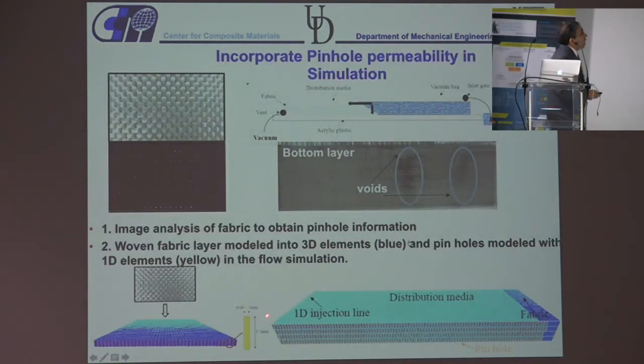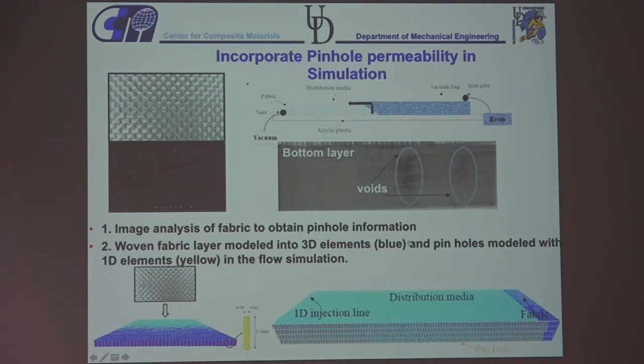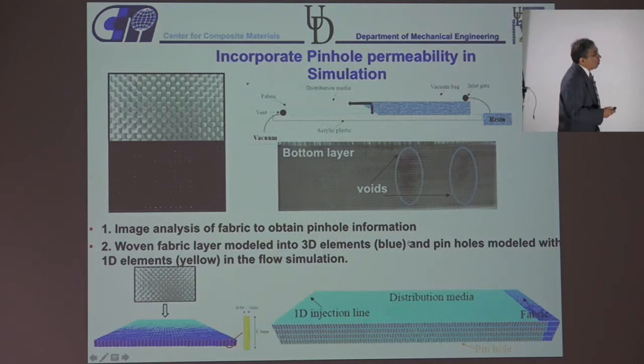So as you can see in here, if I take a fabric and I take a picture of it, these are the pinholes through which the light is going. And notice that no pinholes are the same size, they are not everywhere, and this is the variability that you're introducing in your composite processing. And what happens is if you have a distribution media on top and you're watching from the bottom, you notice that, if you put in a distribution media where the resin goes really fast on the top, you end up with dry areas in here, okay?